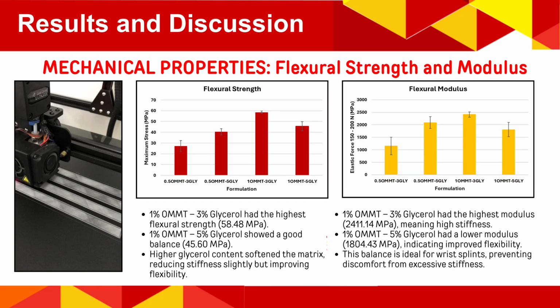Meanwhile, 1 weight% OMMT and 5 weight% glycerol achieved a balance between strength and flexibility with a flexural strength of 45.60 megapascals and a modulus of 1804.43 megapascals. These results highlight the importance of optimizing both OMMT and glycerol content to achieve a comfortable yet durable material for wrist splints.